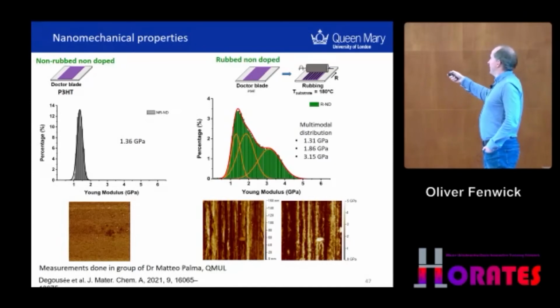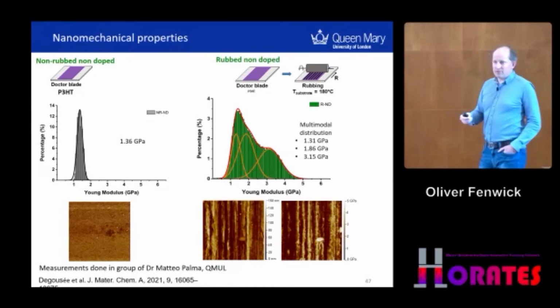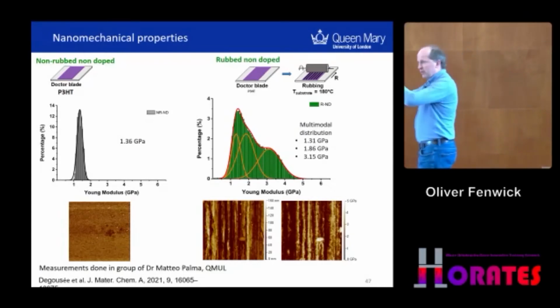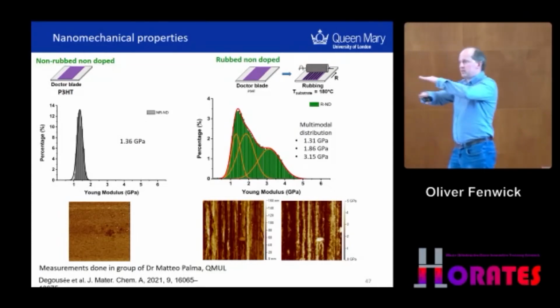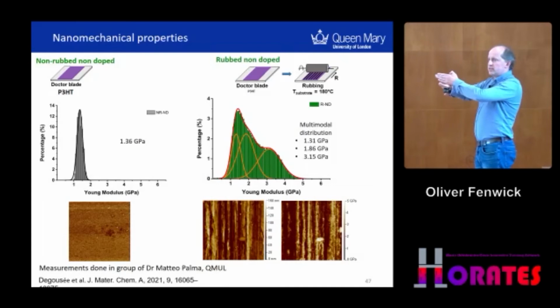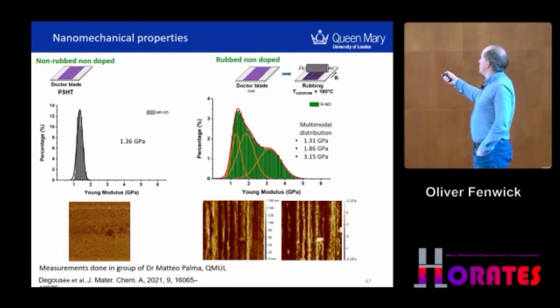Now, this is partly a topographical artifact. Where you have dips in the film, it's quite thin. The tip feels the substrate underneath, which is harder. It's glass. So it's partly related to the topography, but I'll show in a moment that that's not the whole story.